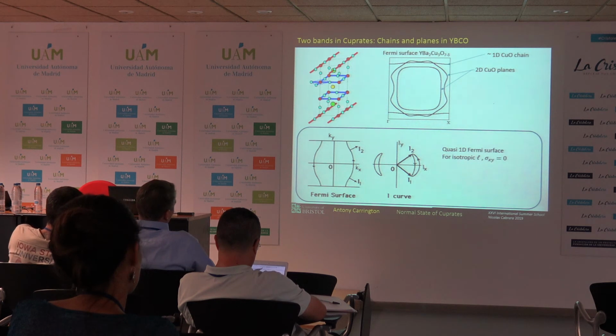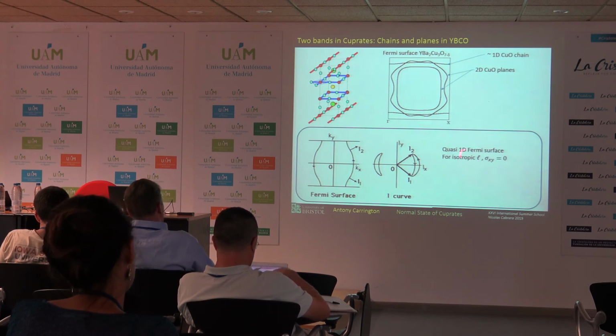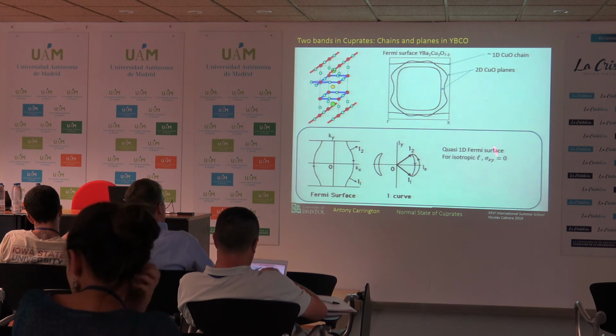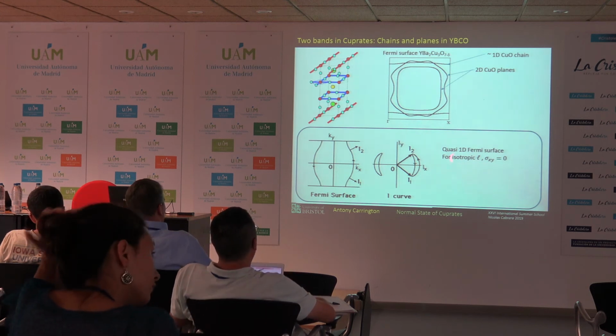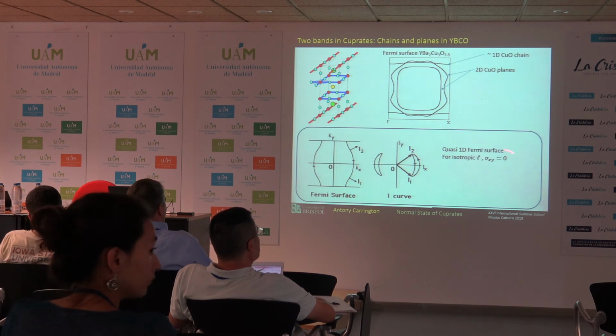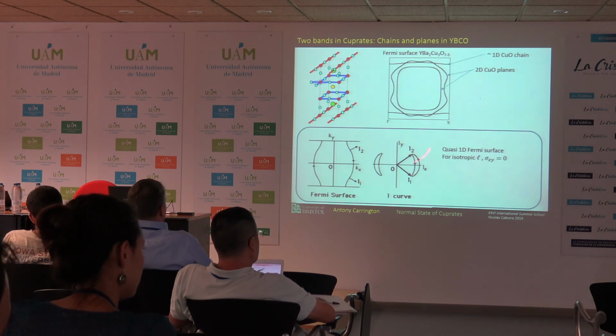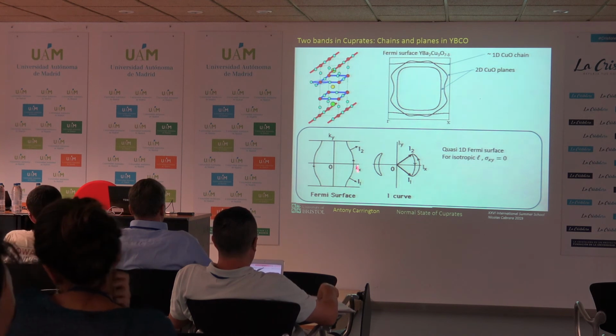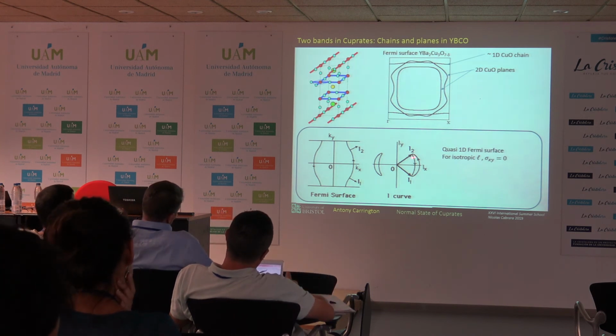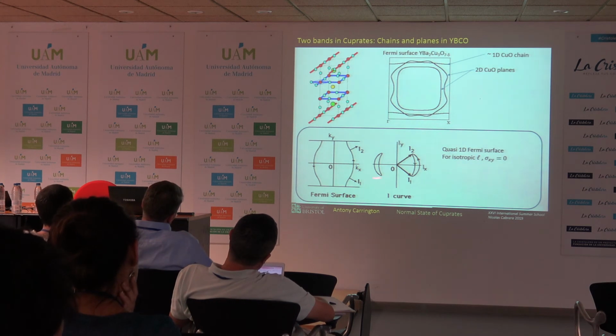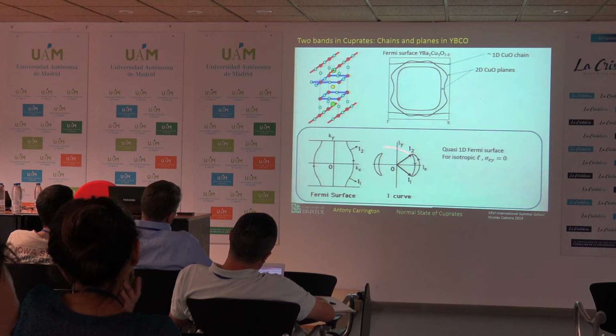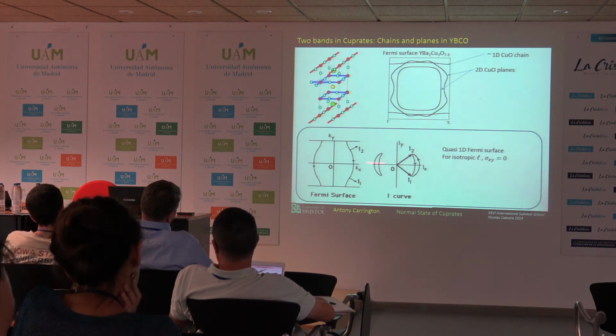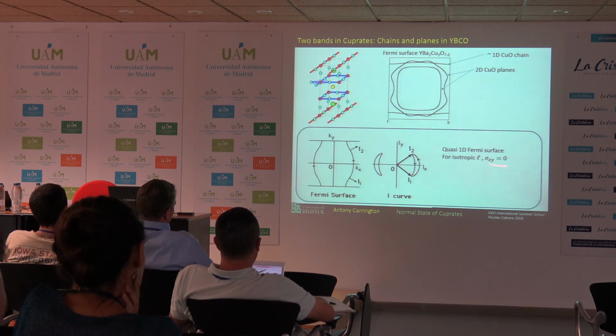Now, within an approximation, and the approximation is that you have isotropic mean-free path, you can show that the Hall conductivity from a one-dimensional Fermi surface, if you've got isotropic mean-free path, is exactly 0. Right? So basically, this is actually a figure from Ong's original article. This is a quasi-one-dimensional Fermi surface. It traces out this kind of banana shape like this, but you also trace out a banana shape of the opposite circulation from the other band, and the two things cancel out to give you 0 area, and so the Hall conductivity is exactly 0.